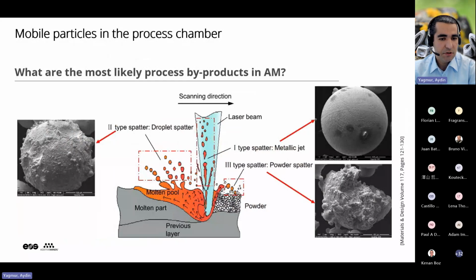As I said shortly, the process can create different byproducts, including so-called spatters, solidified or metallic particles that are spread along the powder bed, and they may have different sources. For example, the very first type is created directly from the keyhole due to the pressure difference, and they can create sphere-like spatters.